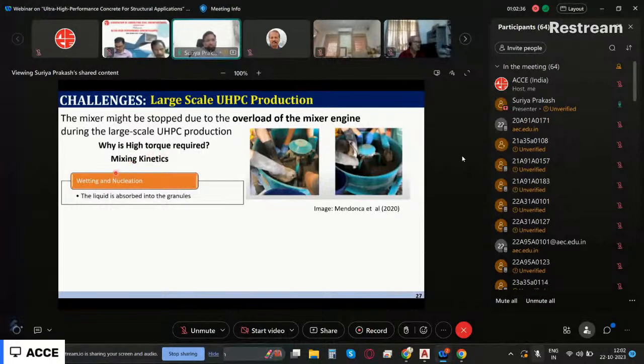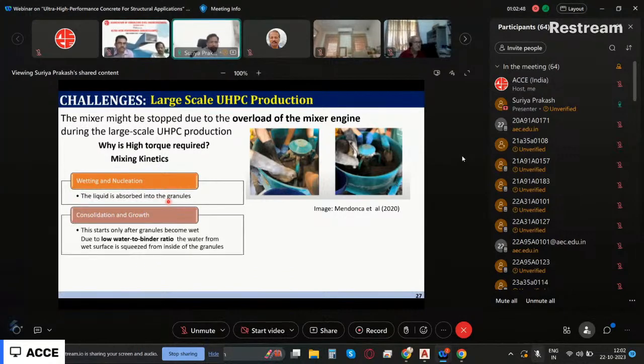Okay, there are different processes that happen. One is a wetting and nucleation process. First, the water that we are adding, or the admixture that we are adding, will be absorbed into the granules, and then you have a process called consolidation and growth, and this will start only after all the granules become wet. Now we are using a low water-to-binder ratio, so the water from the wet surface will be squeezed from the inside of the granule. So these are different processes. Then finally you have homogenization. To get homogenization, I need a large mix time.